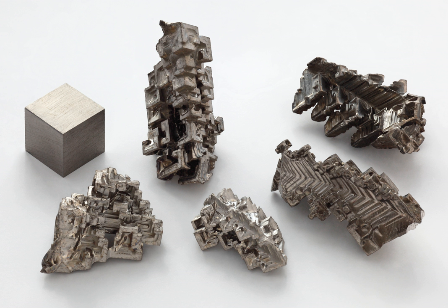Similarly, alloys containing comparable parts of bismuth and lead exhibit a very small change, on the order of 0.01%, upon melting, solidification or aging. Such alloys are used in high-precision casting, e.g. in dentistry, to create models and molds. Bismuth is also used as an alloying agent in production of malleable irons and as a thermocouple material. Bismuth is also used in aluminium-silicon cast alloys in order to refine silicon morphology.